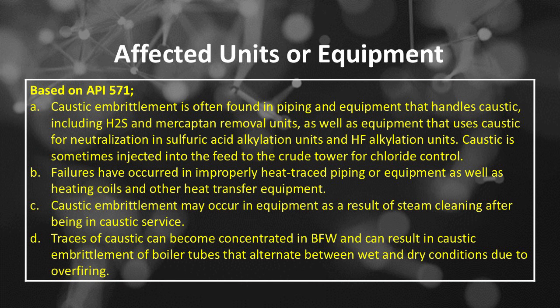Caustic stress corrosion cracking, or caustic embrittlement: damage-affected units or equipment based on API 571. Number A, caustic embrittlement is often found in piping and equipment that handles caustic, including H2S and mercaptan removal units, as well as equipment that uses caustic for neutralization in sulfuric acid alkylation units and HF alkylation units. Caustic is sometimes injected into the feed to the crude tower for chloride control.